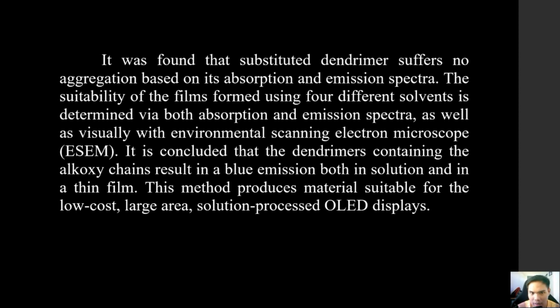The suitability of the films formed using four different solvents is determined via both absorption and emission spectra, as well as visually with environmental scanning electron microscope, or the ESEM. It is concluded that the dendrimers containing the alkoxy chains result in a blue emission both in solution and in a thin film. This method produces materials suitable for low-cost, large area, solution processed OLED displays.